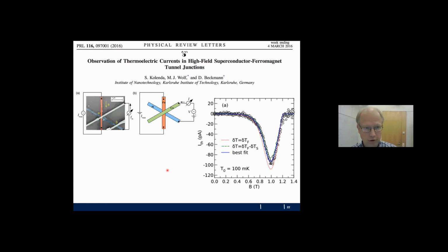Anyway, that was the prediction in 2014, and this was tested by Detlef Beckmann in 2016, and they indeed found a very large thermoelectric current in an experiment. I will not go too much into detail, but basically they heated one part of one electrode with a heating current and measured the thermoelectric current resulting from the temperature difference.